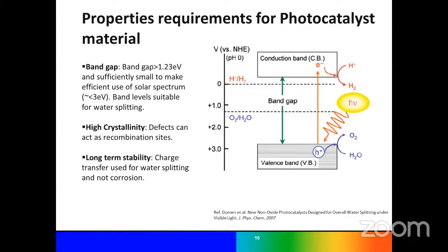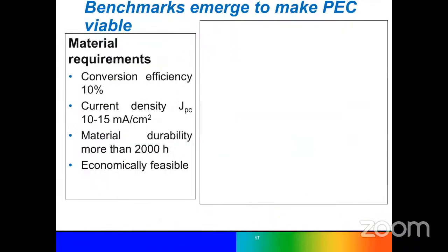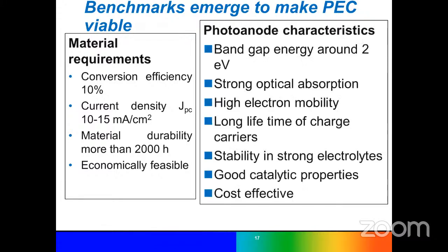Nowadays, the perovskite material is not stable. It actually deteriorates in 1 or 2 days because of the molecular motions of the cation. So that's why long-term stability is more important for using it in water splitting, and it should not be corroded. So here the benchmark is, in the hematite case, a conversion efficiency of around 10% is required to commercialize these water splitting devices. And the current density should be around 10 to 15 milliampere per centimeter square. And it should be durable for more than 2000 hours.